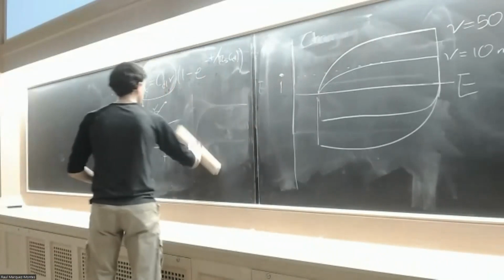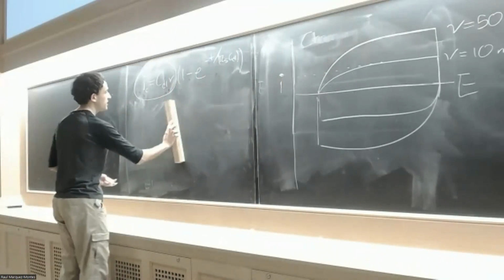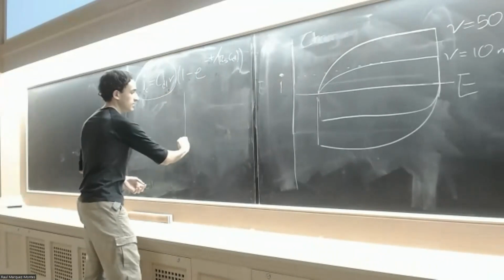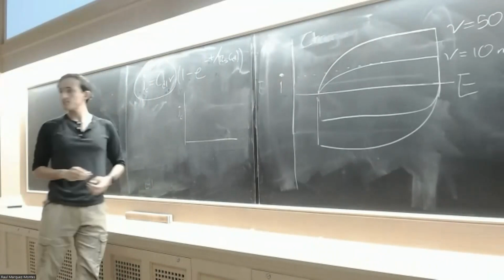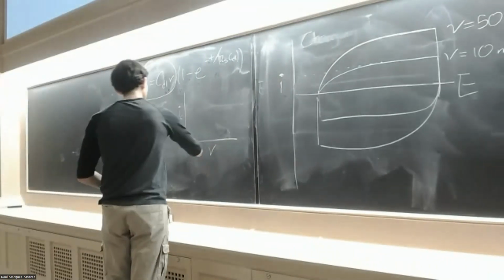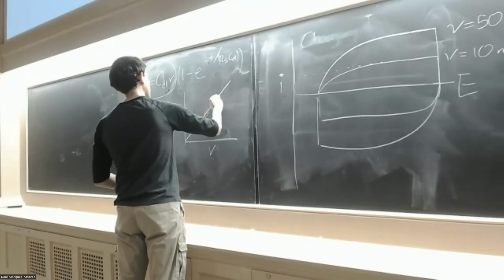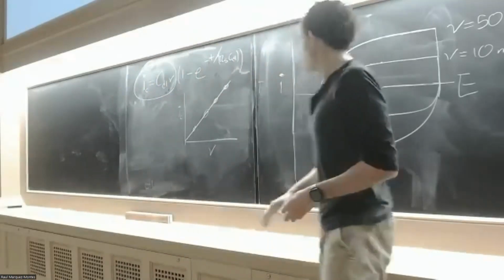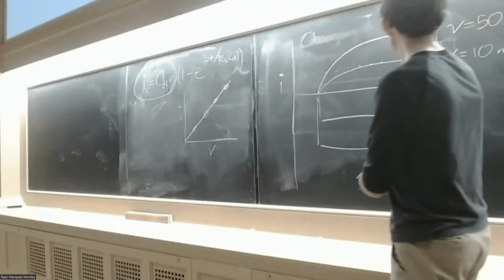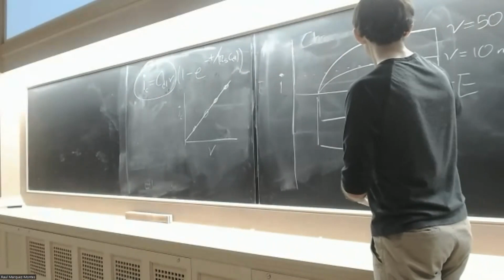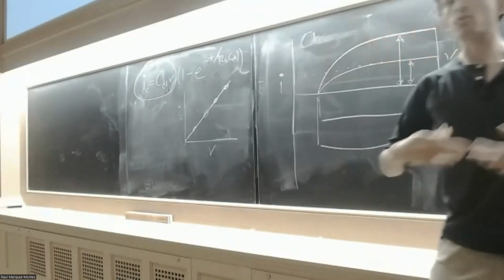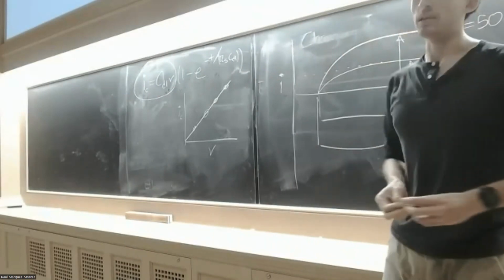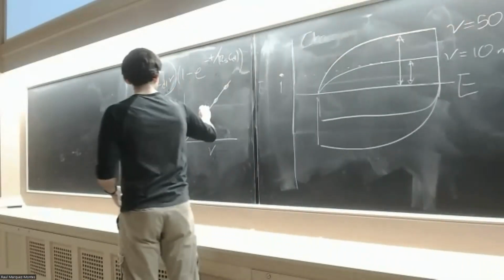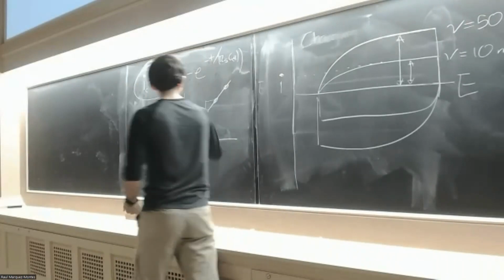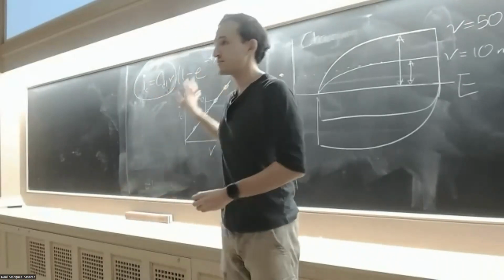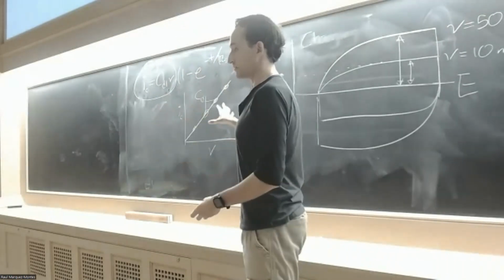How? Move on to this part again. Basically, if we plot the charging current with the scan rate, we should see a linear behavior, because if we increase the scan rate, we should see this magnitude getting larger and larger, and it's proportional to the scan rate we apply. And if we use this plot, the slope equals the double layer capacitance. Does that make sense? This is the general theory about this technique.